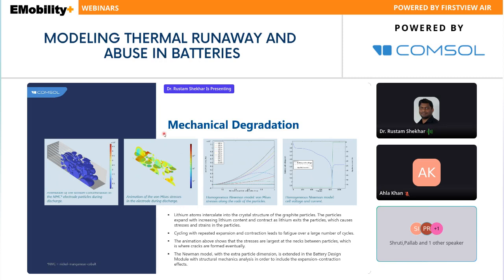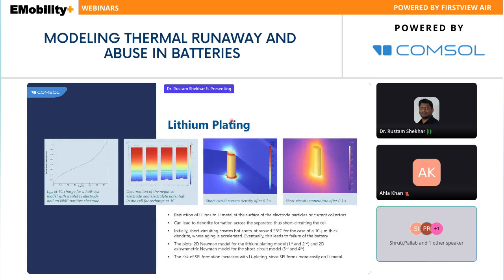Now, if we move ahead, there is one more thing which harms the battery, which is lithium plating. Again for lithium plating, we have taken the same kind of approach, where we model things in 1D when we operate the cell at different kinds of charging and discharging schemes. So we have a 2D Newman's model for lithium plating, and in the 2D model we just see how the dendrite will grow, and you can see, because of the dendrite growth, when the cell will be more prone to failure.